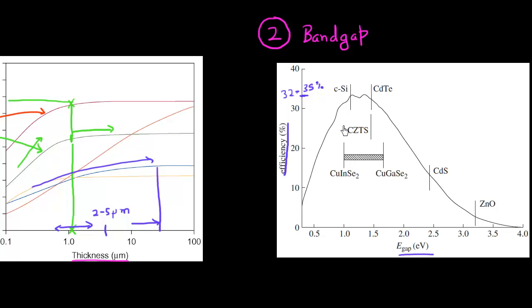So shown here is that essentially if you have your CdTe material or your CIGS material. In CIGS material, in CdTe for example, it has a band gap of around 1.4 eV and that's very nice. For the CIGS material you can tune the band gap all the way from 1.1 to all the way up to 1.5 or 1.6 depending upon what percentage of gallium you add. So if you have no gallium, you just have a CIS cell, then your band gap would be around 1.1 eV. If you have complete 100% gallium and no indium, then your band gap would be high. So you can tune this band gap within this range for the CIGS material. The other material, the CZTS, which essentially replaces the indium and gallium by zinc and tin which are more readily available, and we'll talk about that just now, it also has this optimum band gap.